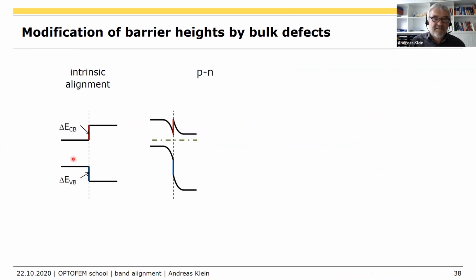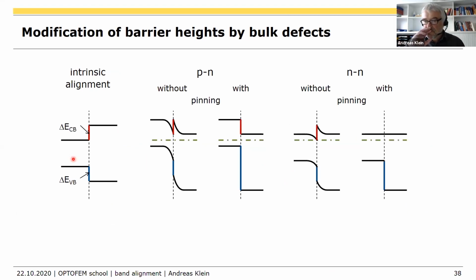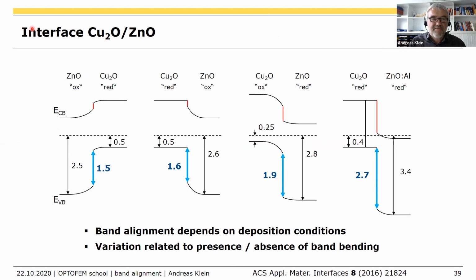And we have a lot of, okay, I can skip that. And that's what we get when we measure the interface between copper oxide and zinc oxide. We measure valence band offsets of 1.5, 1.6, 1.9, 2.7 eV, depending on how we make the material. And you can see, for example, in the copper oxide, if you make the copper oxide in a slightly reduced state, your Fermi level is pinned near 0.5 eV and you don't get much band bending. If you make it with more oxidizing conditions, you have a different Fermi level, and now you can have some band bending in the copper oxide.